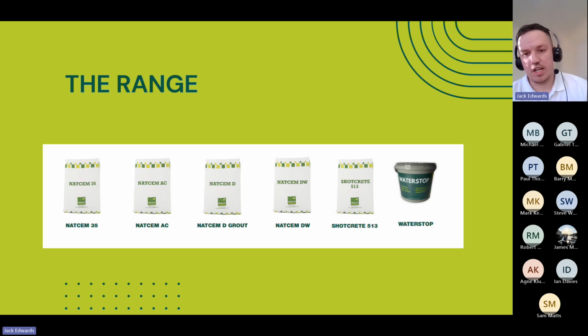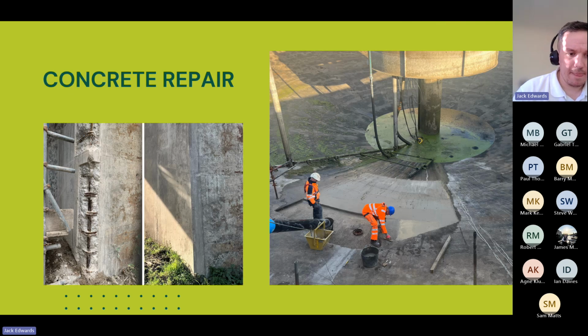That can be used for any dry spray concrete application, whether that be concrete repairs, waterproofing, whatever it may be. And then lastly, we've got our water stop, which is a plug, and you use that for sealing against active leaks. So you've got water penetrating through a concrete structure, for example. You mix that into a putty in your hands, hold it in place over the leak. It sets in a minute and a half to 2 minutes, and then the leak will be sealed. So in a nutshell, that's the core of the range of products that are approved for potable water.